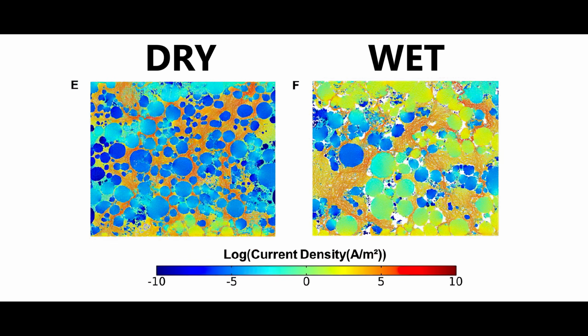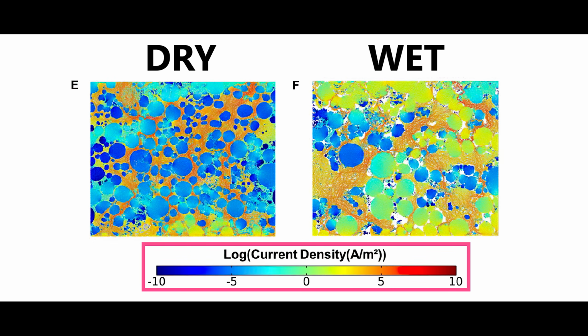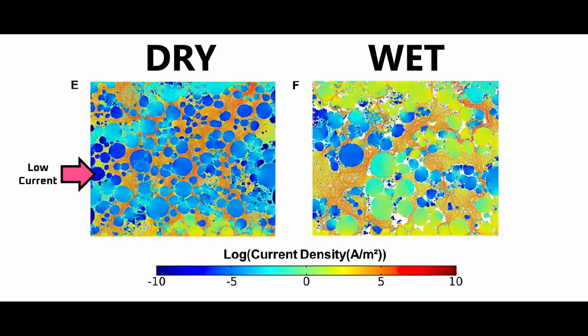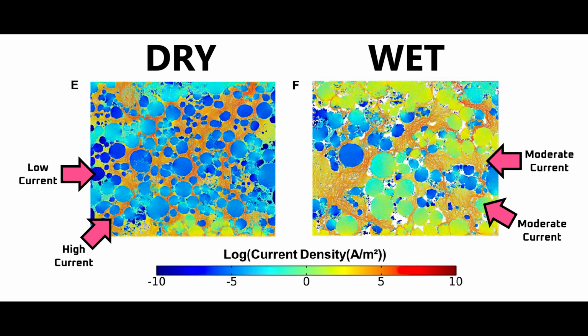The colors indicate current density, ranging from low current density in blue to high current density in orange and red. Image E for dry coating shows that most of the cathode particles are blue and therefore barely used as a current pathway. Meanwhile, the conductive carbon binder matrix is mostly shades of orange, showing that it's the preferred electronic pathway. Image F for wet coating shows cathode particles that are mostly light blue to yellow, indicating heavier use of the cathode particles as an electronic pathway.